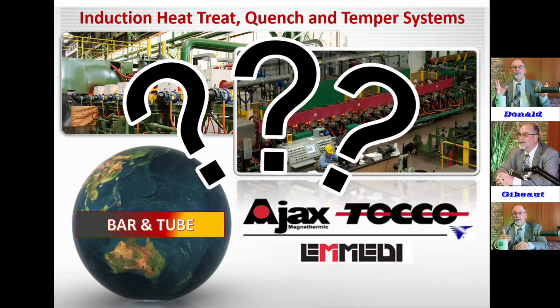We have found we can go higher in temperature on the temper in a shorter period of time, and then we hold that temperature in open air till we get to the cooling bed. Then it's put on a cooling bed and it's brought down to 600 degrees before anything is done. So that's all open air timing. We temper with the same metallurgical structure on the tempered martensite uniformity to a 95+%. So it's very comparable to a furnace, but we do have to bring it up a little bit higher. So hopefully that answered your question.